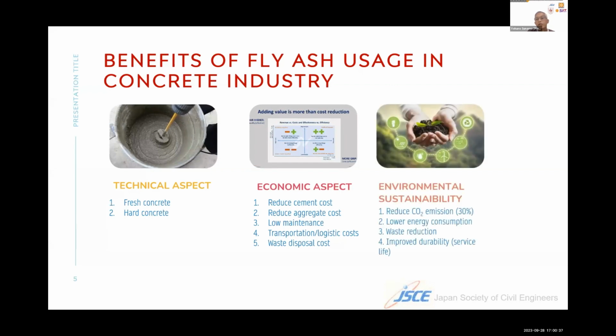The next aspect is environmental sustainability. Fly ash use can reduce carbon dioxide emission because the main component of concrete is cement. And we know that cement production contributes about 6 to 7% of the total carbon dioxide emission into the atmosphere. So by reducing cement consumption, we help reduce carbon dioxide emission. According to some data sources, the use of fly ash for concrete can reduce carbon dioxide emission by about 30% from before.